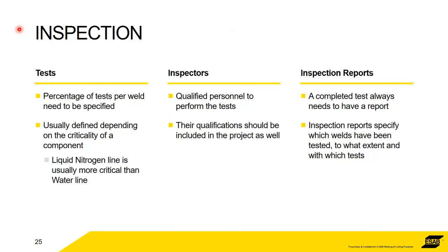Now into inspection. Unlike what Pacific Gas and Electric did, all of these welds, especially the ones in the more crucial sections, need scrutiny. Think about two different sets of piping facilities, one transporting nitrogen at -196 degrees Celsius, and another transporting water at room temperature. You can imagine that the one at lower temperature may have more scrutiny. It's a more problematic weld, especially because at lower temperature, the steel in general performs differently